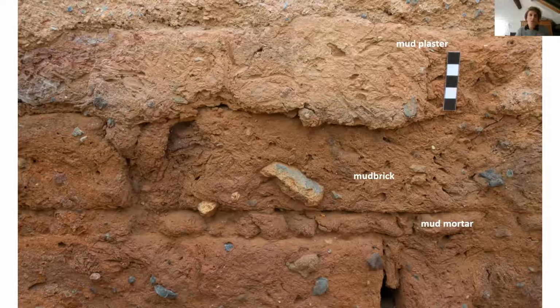And this difference in composition between mudbrick and mud plaster is especially useful when earthen building fragments are found in excavations, since the presence of seagrasses or straw may help to distinguish between mudbrick and mud plaster. On some walls, multiple superimposed layers of mud plaster show the gradual refining of the mud plaster composition, with a thick layer, 3 to 10 centimeters, of coarse mud plaster used to even the surface of the wall, on top of which one or several fine layers of mud or lime plasters were applied.